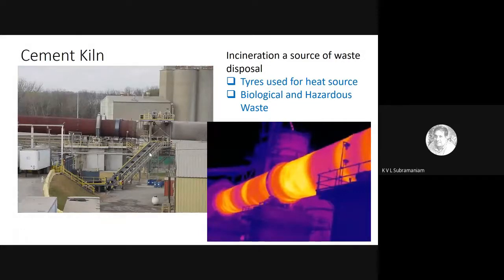And on the right hand side, you see a photograph. It's an infrared photograph which shows the temperature of the kiln. One cannot get an idea of the temperature unless one takes an IR image, and you can see that it gets really hot inside the kiln.